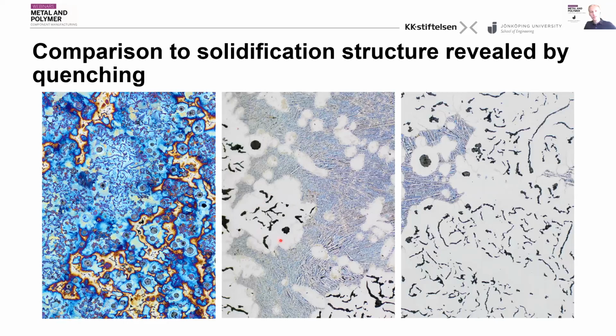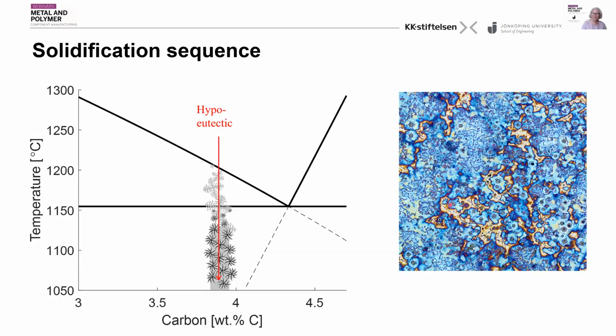You can also see that we have these eutectic cells of compacted graphite, and that we have shells of austenite around the spherical graphite, which you can also see as blue auras around the spherical graphite with the color etching. So what you will see with the color etching depends on how the material has solidified, and it reflects, in some sense, the early solidification structure of the material.